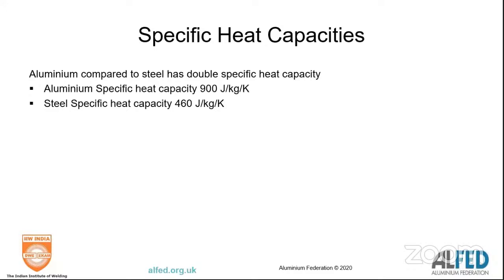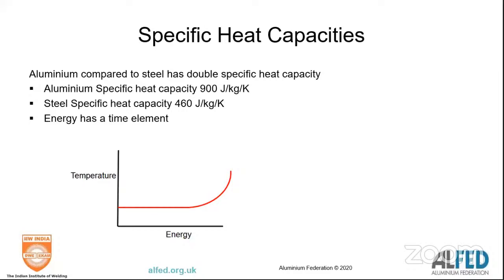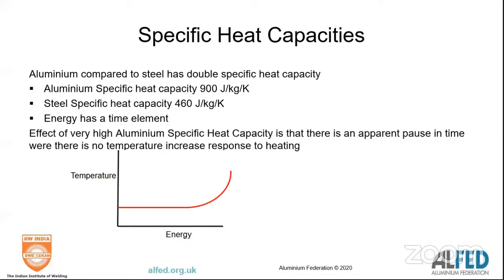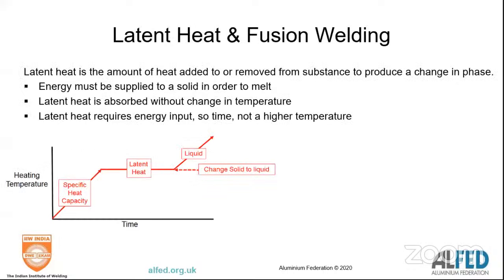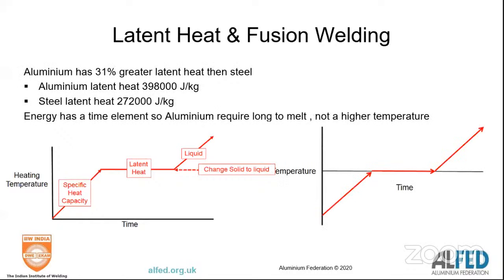So aluminium has double the specific heat capacity of steel, and that has a time element. In essence, what that means is when you put energy into aluminium to heat it up, nothing happens for a period of time, because what you're doing is raising its specific heat, and then it sails away. So with aluminium, what we have is a time element, because energy has a time element in it. When you talk fusion, so we've raised the temperature of the solid. When you come to fusion, you've got latent heat. Latent heat changes solid to liquid, and aluminium again has a third higher latent heat. So again, what you need to do is put more energy in, but you put energy in terms of time. You pause to put the energy in rather than turning up the temperature. So many people, when they're welding aluminium, think nothing's happening, and the normal thing is to turn the welding temperature up, and then you just end up with a melt, a disaster.